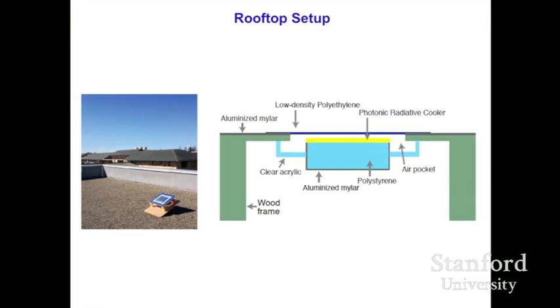In reality, if you like to operate this, you don't have to do it this way. You can put it flat, and the performance, if you do it right, would have been better. So one of the things that's quite important about the roof is that the roof is actually a very hot place. Anything that's on the roof under the sun gets heated up. So as a result, everything that you see here actually has a temperature much higher than the ambient air temperature. Our objective here is to use this cooler to get to a temperature below ambient. And so this is, roughly speaking, like trying to demonstrate cooling in an oven.